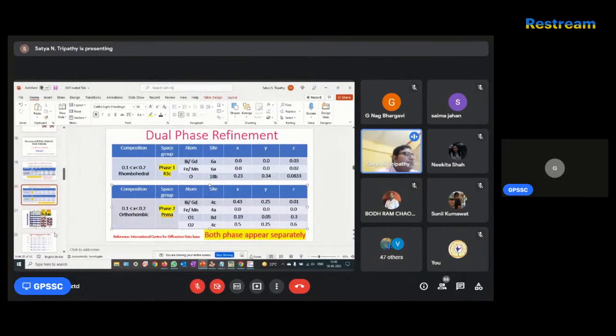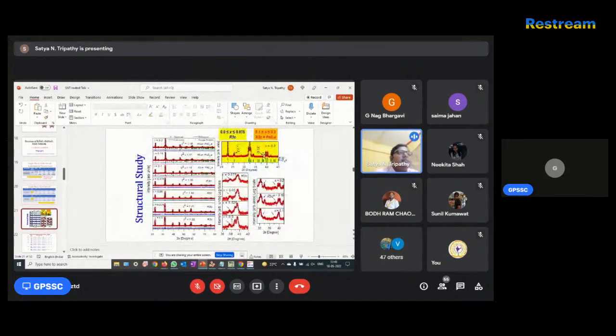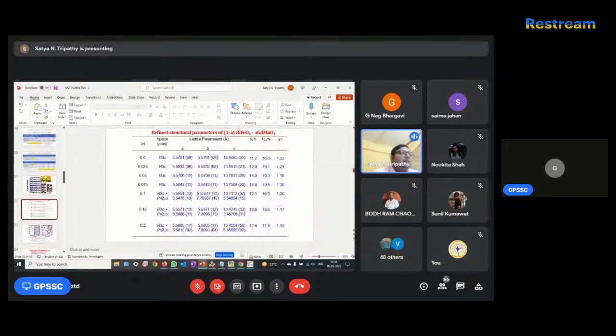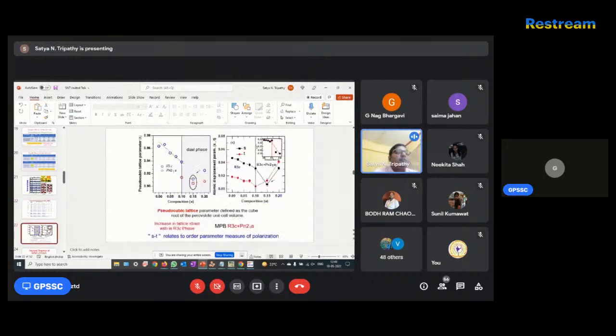Okay, so this is the XRD data, and based on that, we have done the Rietveld refinement. Next, we have calculated the lattice parameters the way I showed you in the refinement process. And next is how to analyze the data. On the x-axis, I have plotted the pseudo cubic lattice parameter versus composition. For the pseudo cubic lattice parameter, suppose you have R3C, you go for the volume. The volume will be 374 angstrom cube, and there are 6 unit cells.